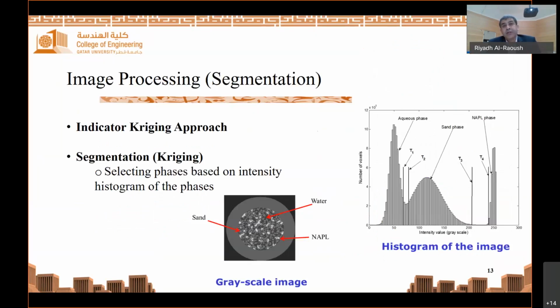As I mentioned, there are so many segmentation algorithms available, and this is very critical for our analysis. Here I show just an example of an image segmentation technique, which is the indicator kriging approach. In this method, phases are identified based on the histogram of the intensity values in the image. You can see here a grayscale image obtained from computed tomography that has 3 phases: sand, water, and oil. And this plot shows the corresponding intensity histogram of the image.